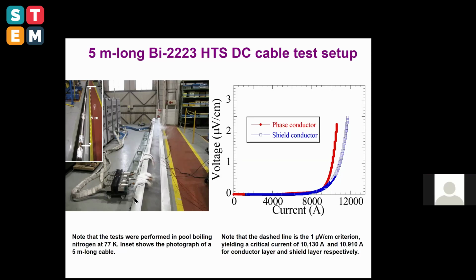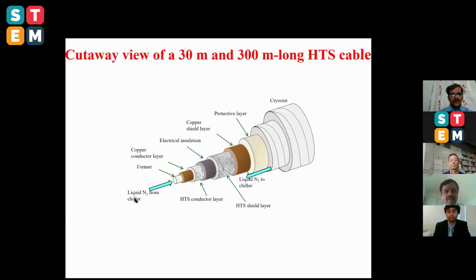Then in the next design we improved the superconducting tapes to further improve the performance. Then this is the final 30-meter and 300-meter long HTS cable. Here you can see the liquid nitrogen pass from here. This is the copper protection layer and the HTS conducting layer. Then the insulator. Then the HTS shielding layer and the HTS protection layer. So the liquid goes from the center, but then it comes back through the protection layer. So this cryostat, everything was designed.